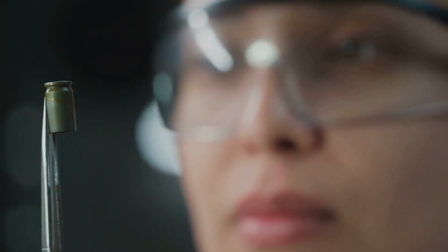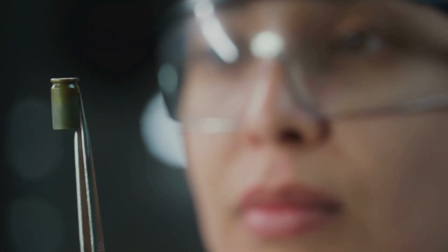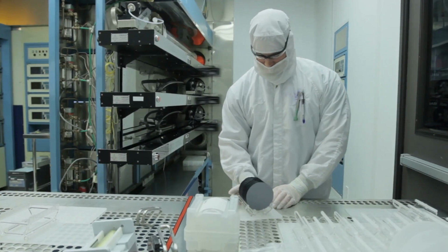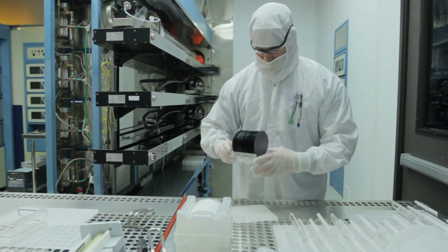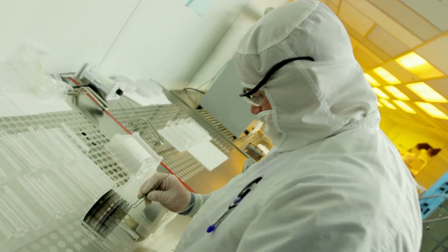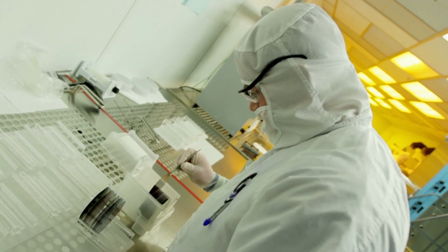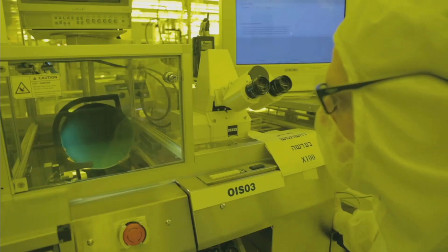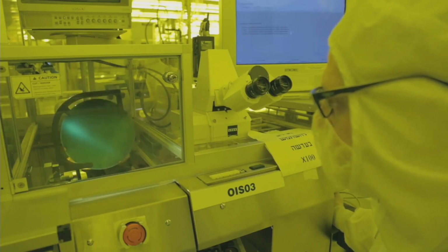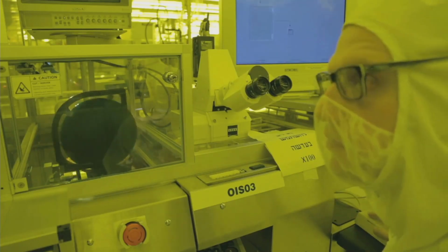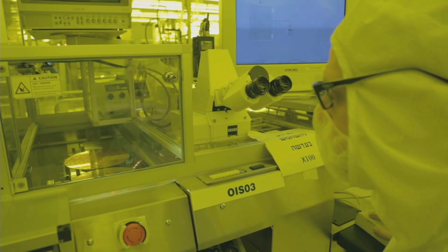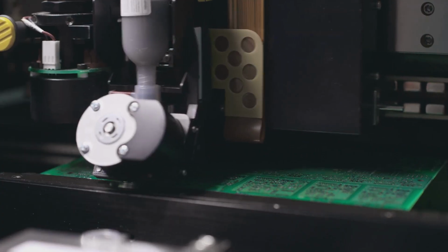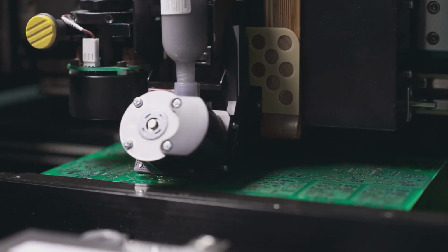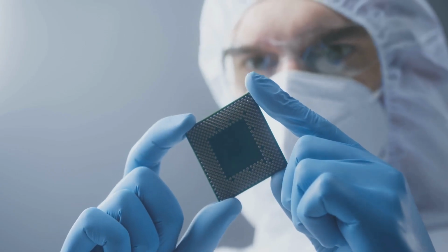The geometry of these nanosheets represents the crucial advance. Each sheet is typically 5 to 10 nanometers thick and separated by insulating spacers. During fabrication, engineers grow alternating layers of silicon and silicon germanium. The germanium serves as a sacrificial material that is later removed. After etching the sidewalls, selective chemical solutions dissolve the germanium, leaving open spaces that become the channels. Metal gate materials are then deposited to wrap around the remaining silicon layers. The result is the distinctive gate all-around design.